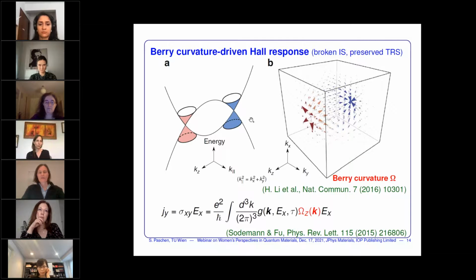So this is the electronic structure of a Weyl semi-metal, and the Weyl nodes are known to be sources and sinks of something called the Berry curvature. And that Berry curvature actually has an effect on moving charges as if it were a magnetic field. You can see that from this equation here, where this is the out-of-equilibrium distribution function of the electrons just driven by electrical current. So it was predicted to have this effect, but the effect was expected to be extremely small, to the level that it could not be detected.